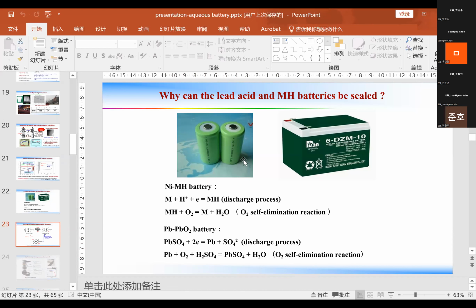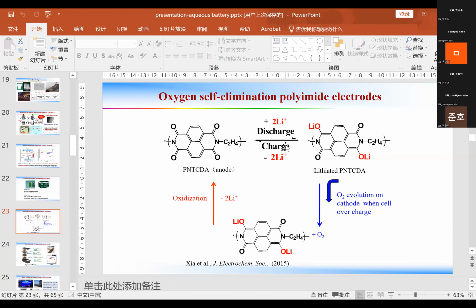This suggests that for the aqueous lithium battery, we must find some oxygen self-eliminating electrode. Then we can seal the aqueous lithium-ion battery. We took over two years to find this. We found that some polyimide electrodes can have the oxygen self-elimination function. It is also an active material in the discharge process: the carbonyl bond will open, and then combine with lithium, so it can store the energy, can store lithium. But this material can be chemically oxidized by oxygen and go back. So this is a self-eliminating electrode material.